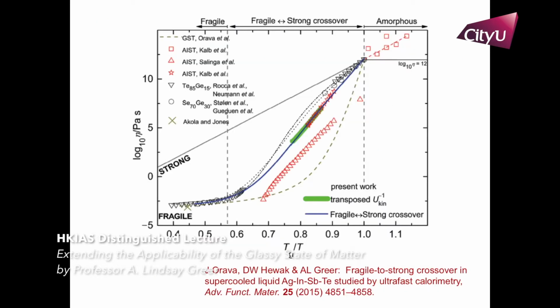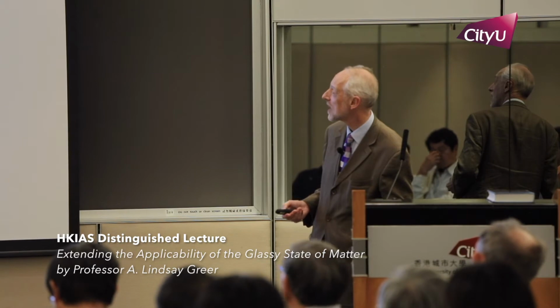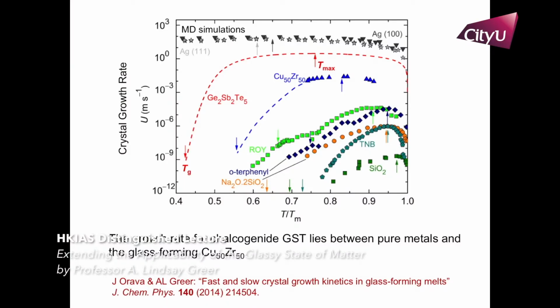This is our chalcogenide showing this Arrhenius portion. And the really neat thing here is that the high temperature fragile liquid is essentially metallic, and the low temperature strong liquid is semiconducting. So you get an electronic transition as well as the structural one, which of course is of extreme interest for device performance. This just shows the range of crystal growth rates and is my very final topic. Here's our chalcogenides, high crystal growth rate at a particular temperature range. And because the crystal growth rate is high, the switching is fast. And because the switching is fast, this is a viable memory technology.